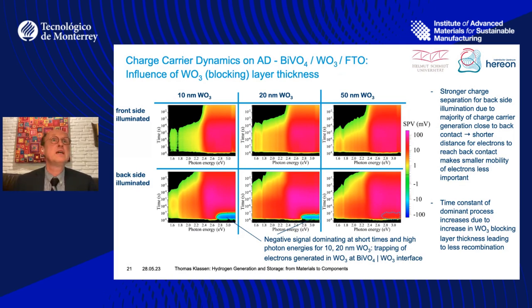So here you see a special method. It's quite complicated surface photovoltage measurement. So you have a laser that's irradiating your surface, and you probe the reaction some fractions of a second afterwards to see whether your charge carriers are mobile or stick to the surface. It's a very small device, actually, self-made, but it's quite effective in telling you what's going on.